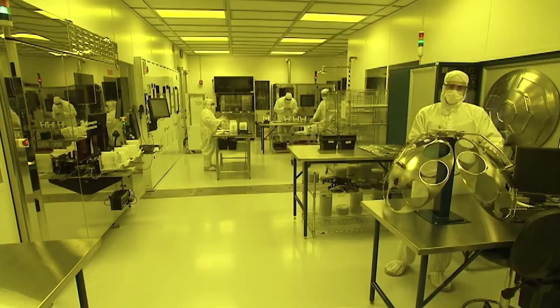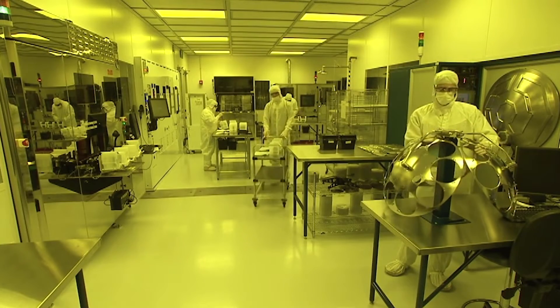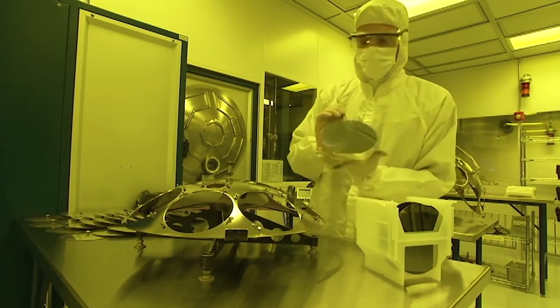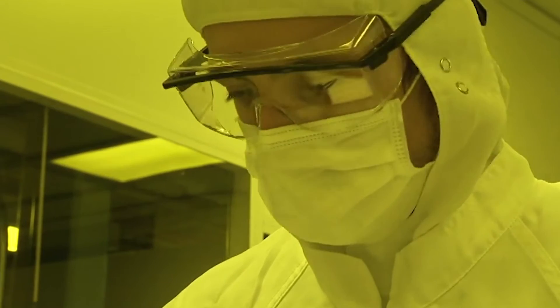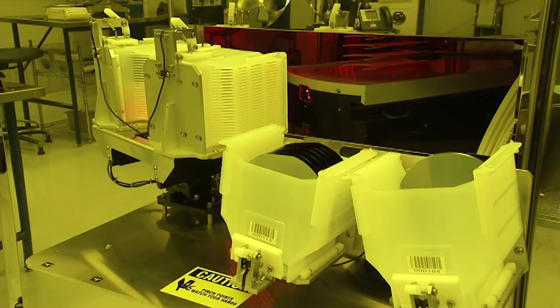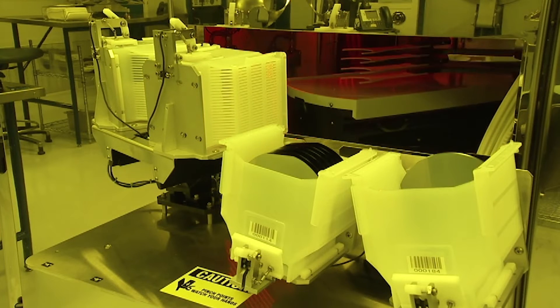We're now outside the solar cell wafer processing room with Jhonti Singh, a technician. In this area, we develop the grown wafers into manufactured solar cells. We go through almost 30 different processes — including anti-reflection coating, metal coatings, etching processes to remove unneeded material, and grinding to lessen the weight of the solar cells. At the end, we heat them up to temperature so all the materials bond together.